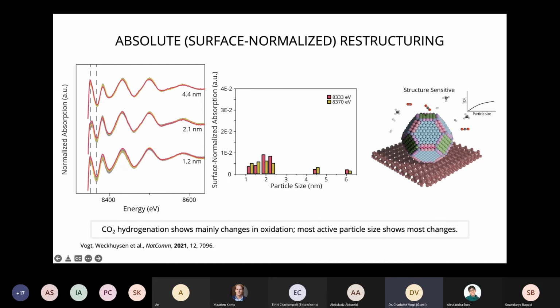In fact, X-ray absorption spectroscopy can be quantitative, and we were able to quantify the surface normalized restructuring that we observed using that technique. So we took two different spots. We took the white line, most indicative of the oxidation state, I would say, for nickel, and we took a point a little bit farther on, which is starting to go towards geometry. And we compared the change that we saw going from reduced to reaction for, in this case, CO2 hydrogenation, in the next slide for ethene hydrogenation, and compared that change for the different nanoparticle sizes.